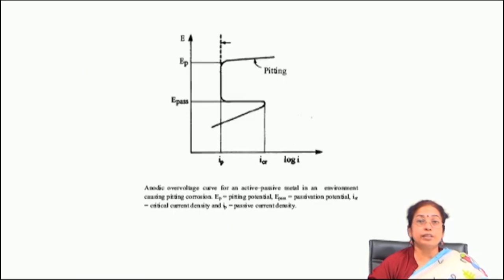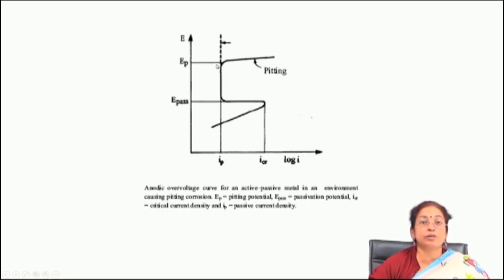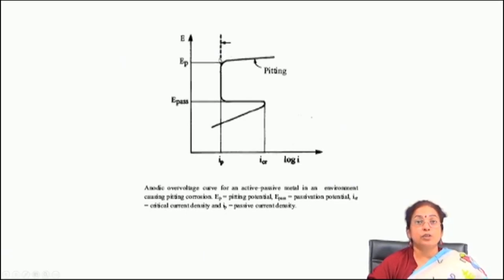If you are interested to evaluate the pitting corrosion rate, you have to know the area fraction of porosity with the help of microstructural analysis, or you can measure it by electrochemical means. In a component which has undergone pitting corrosion, there is a sharp change in the passive to transpassive zone. That junction point — the intersection between the passive and transpassive region — gives you the pitting potential (E-pit). Higher E-pit potential means higher resistance of the metal to pit formation. The pit initiation potential can be easily measured by electrochemical techniques, and if you are interested in the pit propagation potential you have to do cyclic polarization.